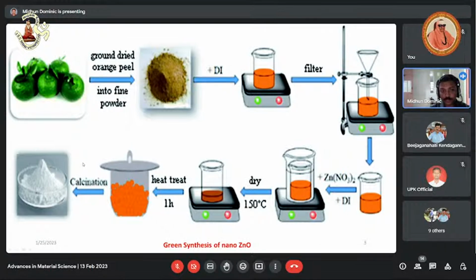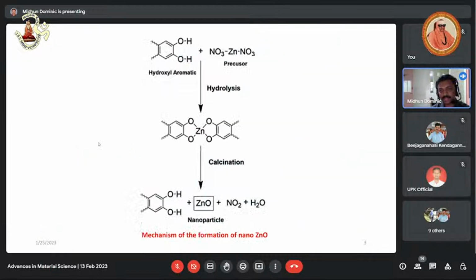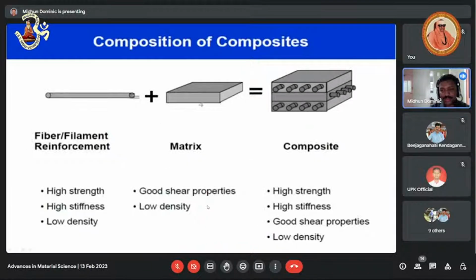So this is a bioreduction method, or green method, for the preparation of nano zinc oxide. We have used an orange peel extract for the preparation of zinc oxide. The mechanism is illustrated like this. The orange peel extract is a rich source of several flavonoids, carotenoids, and limonoids, etc. They are represented as hydroxyl aromatics. They have a number of OH groups, and these hydroxyl compounds may form a complex with our precursor or starting material, zinc nitrate. This is the compound formed, and when we calcinate this complex, we may get zinc oxide nanoparticles.